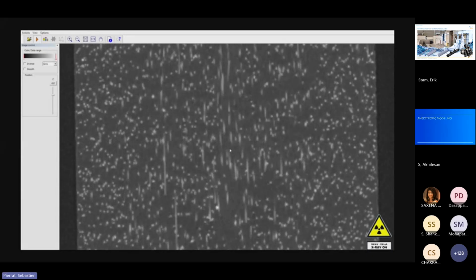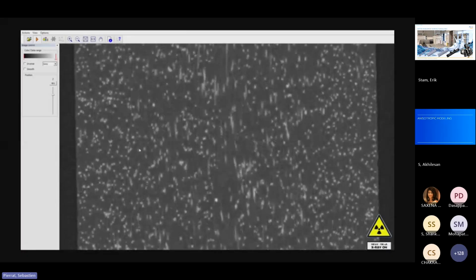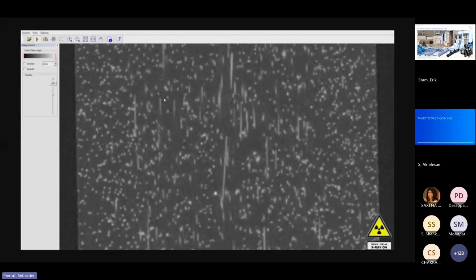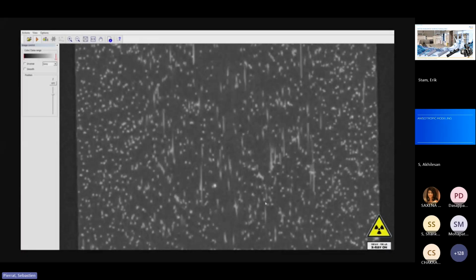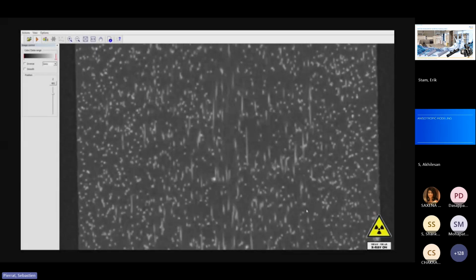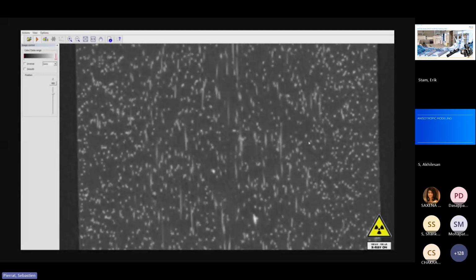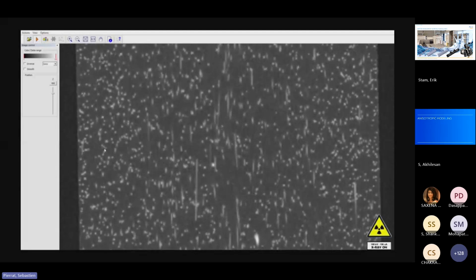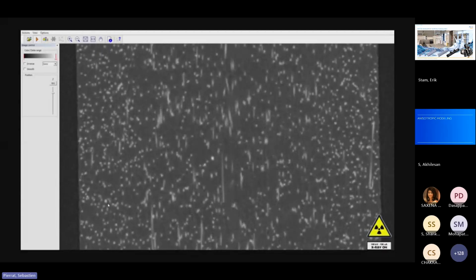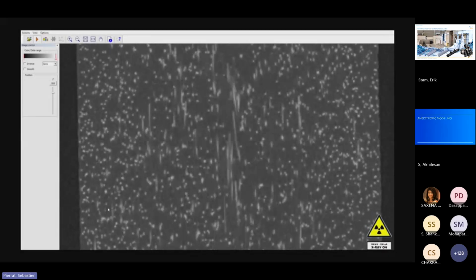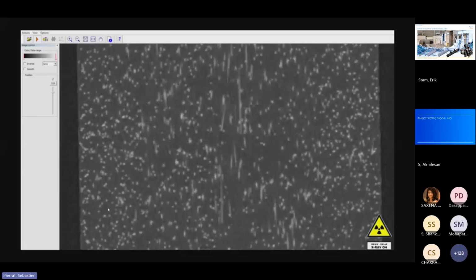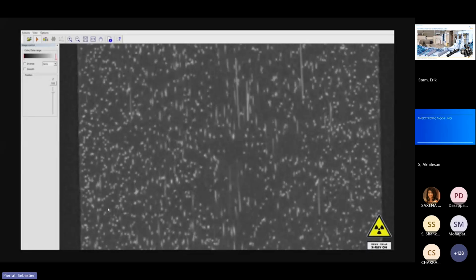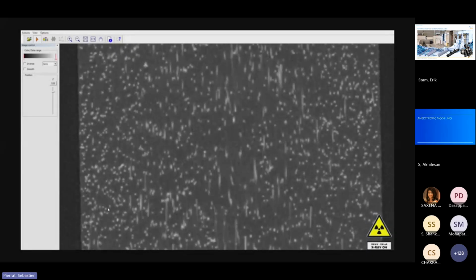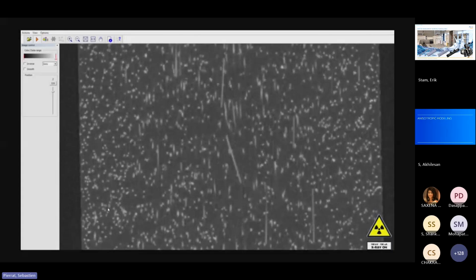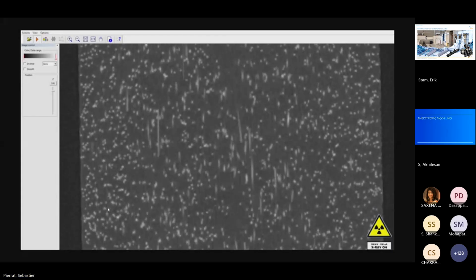The bright spots correspond to the individual glass fibers, and we can see already that they present different orientation in the core of the sample as compared to the surface of the sample. This can be further quantitatively characterized to support the engineering team and provide some data points to validate the simulation.